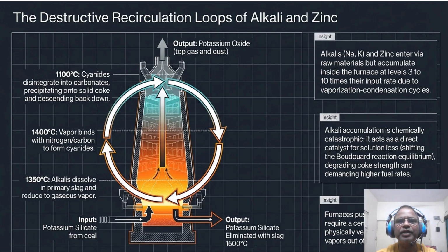Alkali reduce to vapor at 1400 degrees centigrade. They bind the nitrogen and carbon to form cyanides, and at 1100 degrees centigrade they precipitate onto solid coke. This is chemically catastrophic because it acts as a direct catalyst for solution loss, shifting the Boudouard reaction equilibrium and degrading our coke strength. So this demands high fuel rates and ruins the permeability we have worked so hard to maintain.